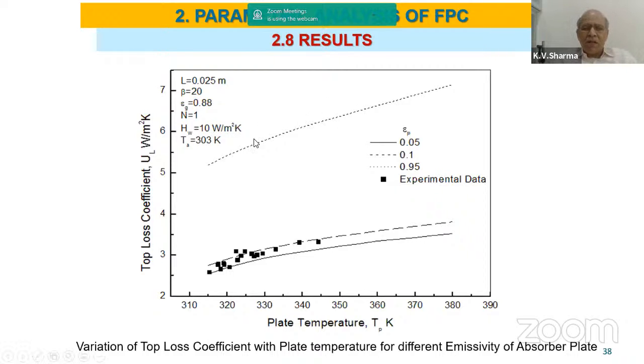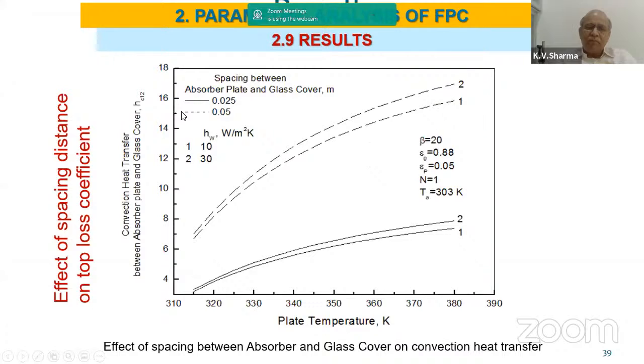And as the emissivity increases, the top loss coefficient also increases. From this figure, we see that the top loss coefficient can vary from about 2.5 to about 5.67, depending upon how the system is. Now, if I change the spacing between the glass covers, if I increase the spacing from 0.025 to 0.05, or from 2.5 centimeters to 5 centimeters, I see that the loss coefficient is increasing significantly. It goes up to 17. So when the top loss heat transfer coefficient increases, it means the losses are going to increase significantly. That is why in the Indian standards, about 2.5 centimeters should be the spacing between the absorber plate and the glass cover.